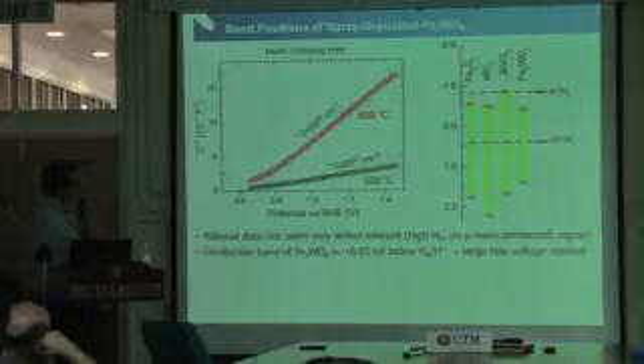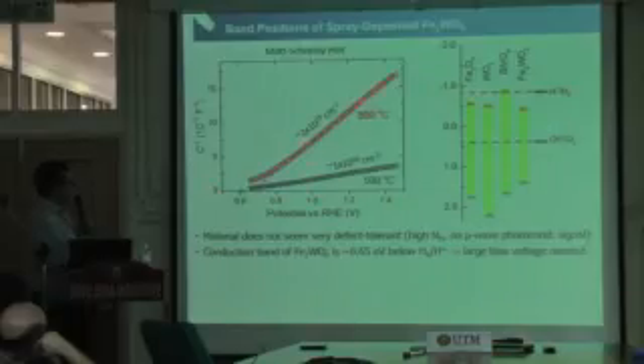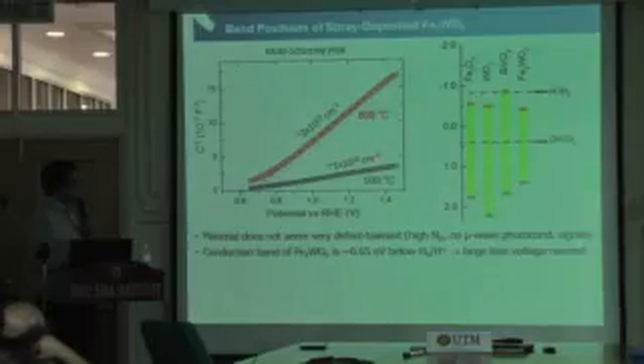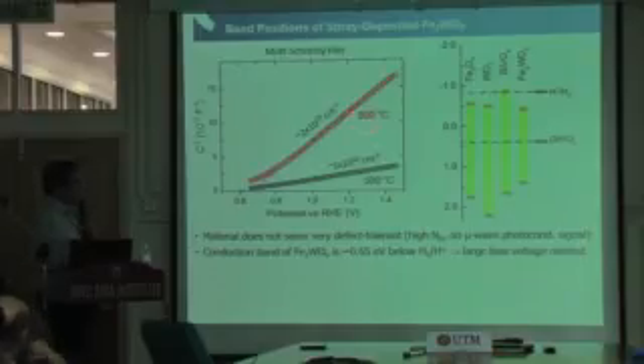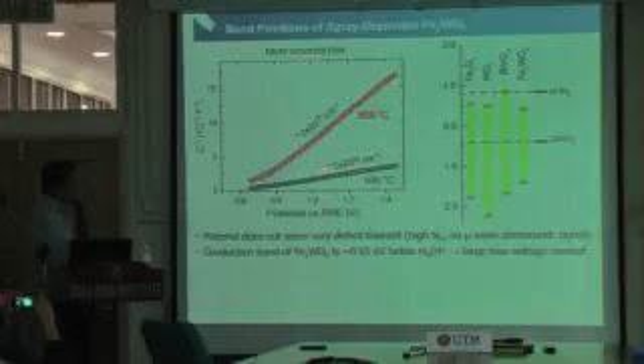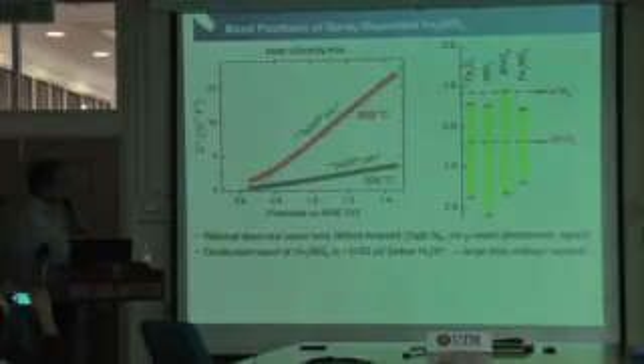And this is a Mott-Schottky plot, so it's 1 over C squared as a function of potential. Basically, we try to get the carrier concentration, and the carrier concentration is really high. If we go from 500 degrees C, as deposited, it is at 10 to the 20, and we anneal it to try to reduce defects and get rid of this probably unnecessarily high carrier concentration. We're only able to go down to 2 times 10 to the 19.